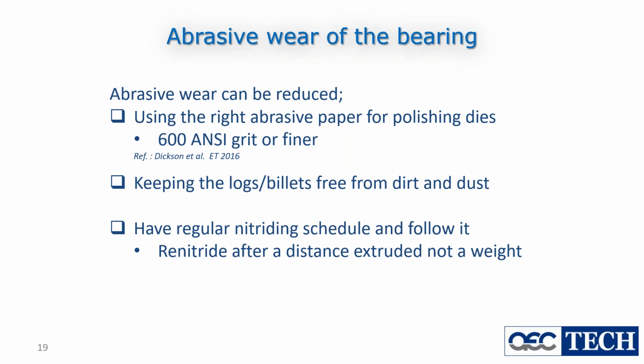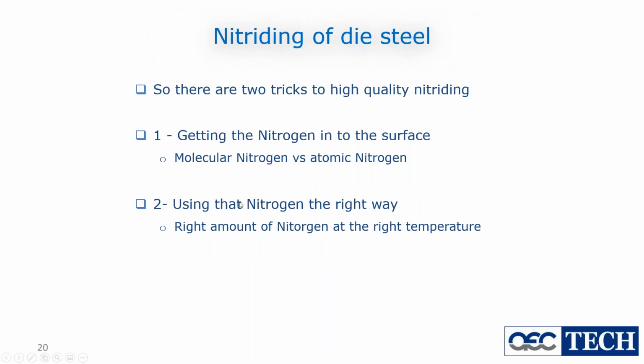If you overcook these dies either in preheating or in use, you can be pretty destructive to this nitriding layer, even though it is a good strong layer. And we strongly recommend that you calculate your time between nitriding intervals, not on number of billets, not on pounds extruded, but on the length that is extruded through the die. Because if you're pushing a little tiny thin section, you'll get a much longer run out on that cavity than if you're pushing a great big heavy 2-inch bar. So it's not pounds. Let's do our re-nitriding schedules based on extruded length.